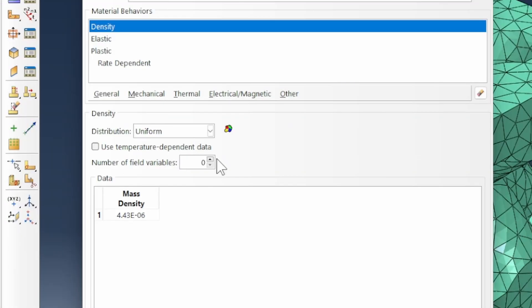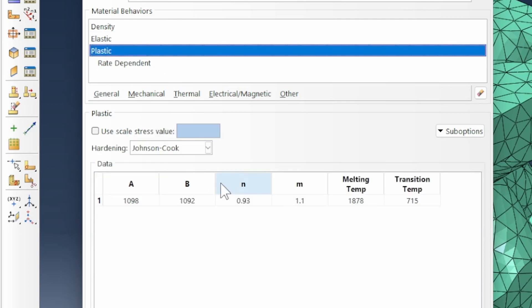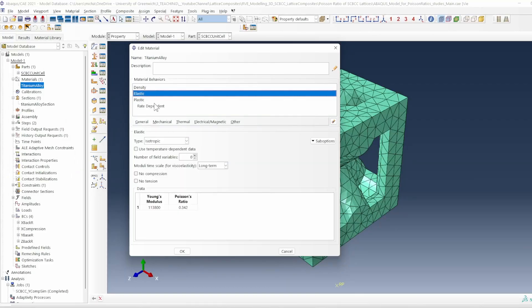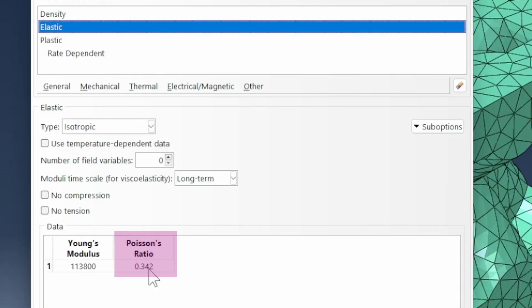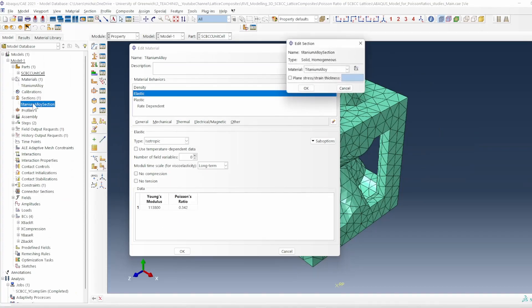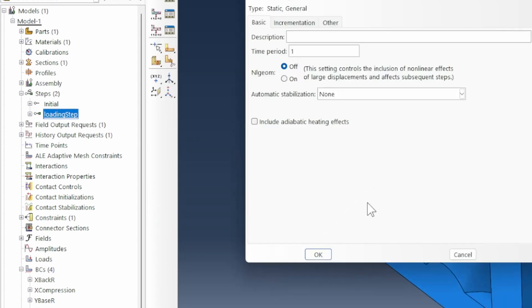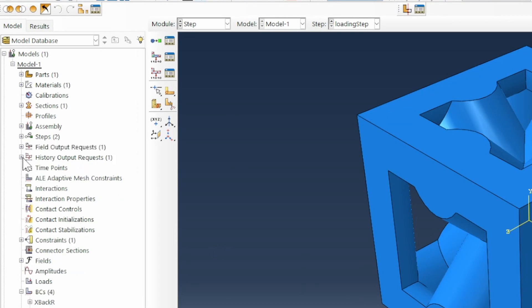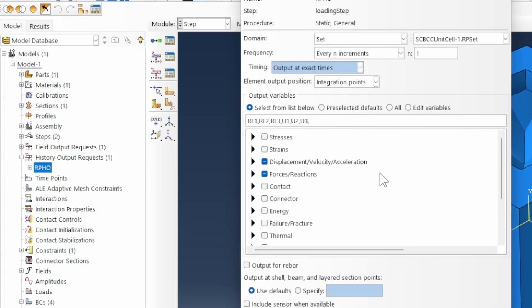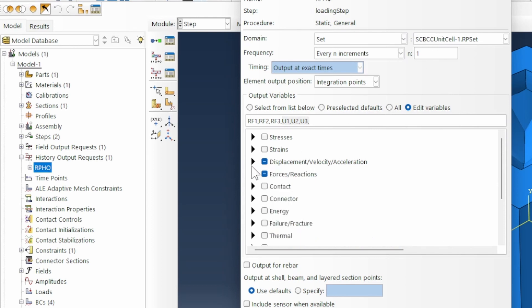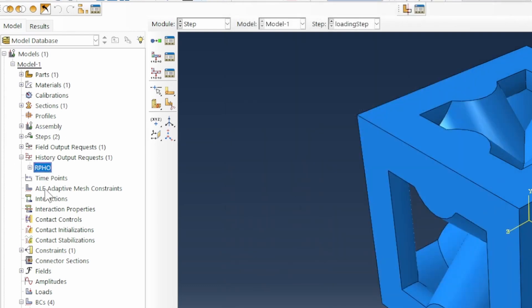The material is a titanium alloy with density, elastic properties, plasticity using a Johnson-Cook hardening law, and a rate-dependent model. The key value is that the bulk titanium alloy elasticity gives a Poisson ratio of 0.342 — we should recover something close to that but different due to the lattice structure. A static general loading step was created, and history output tracks reaction forces and displacements in XYZ for the reference point set.